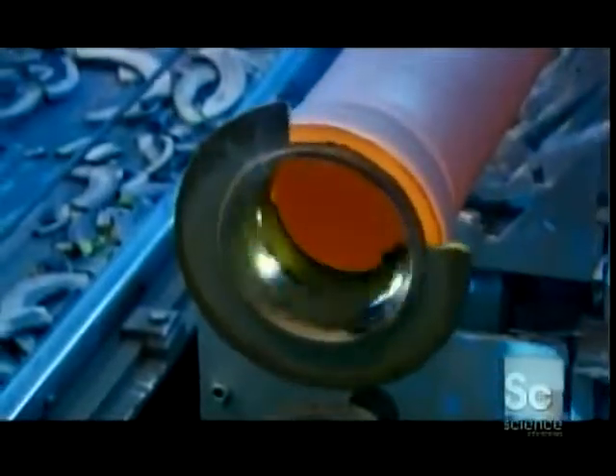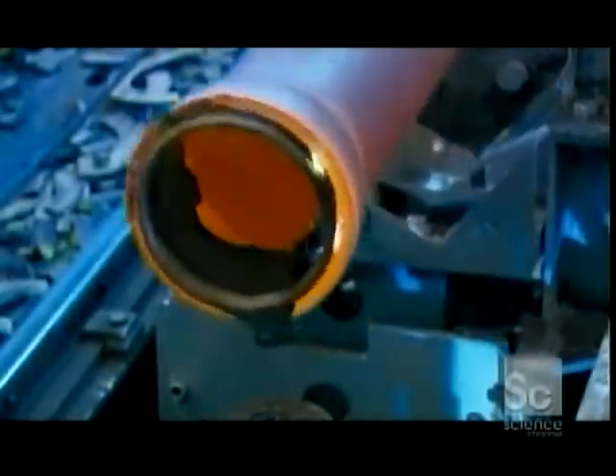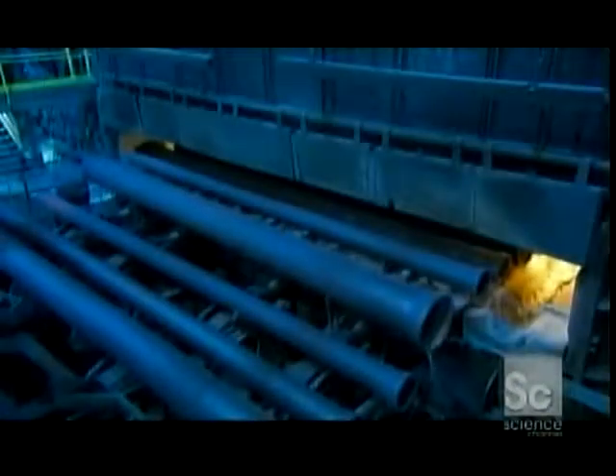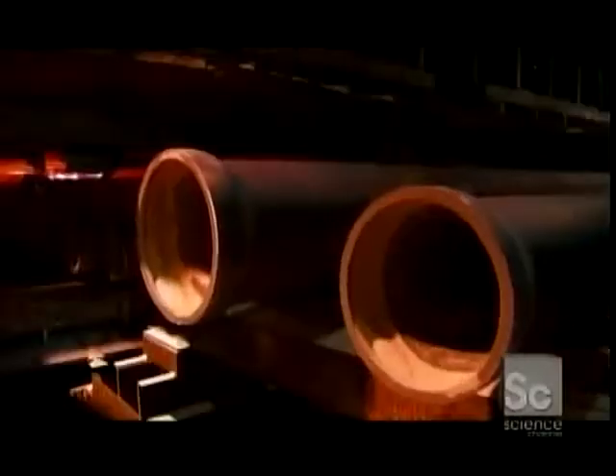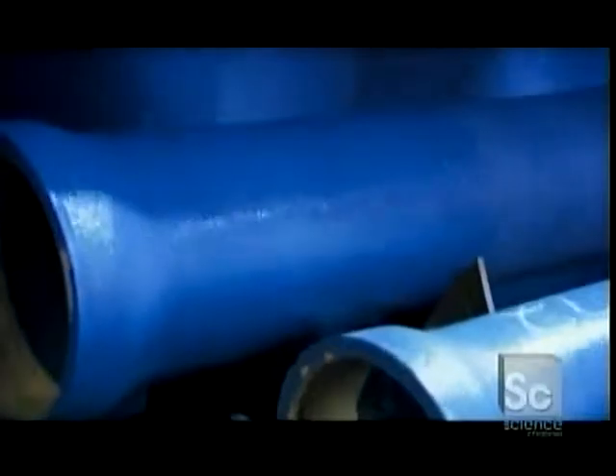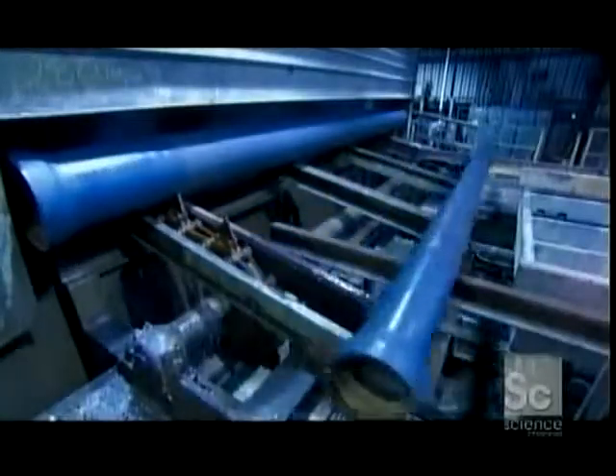Such rapid cooling makes the iron brittle, so the pipe goes directly into a gas-fired annealing furnace that reheats it to 1,700 degrees Fahrenheit. This alters the internal structure of the iron, making it strong and flexible. The pipe then runs through a cooling chamber that showers it in cold water.